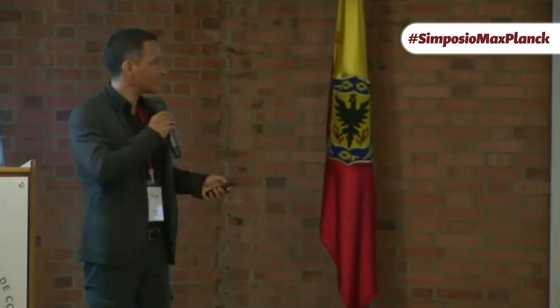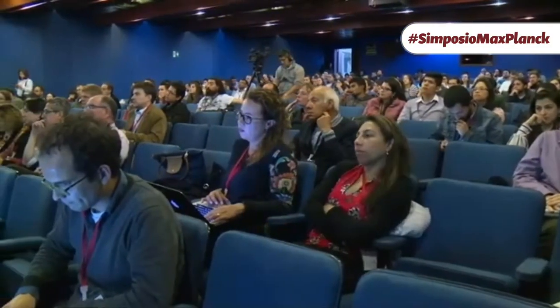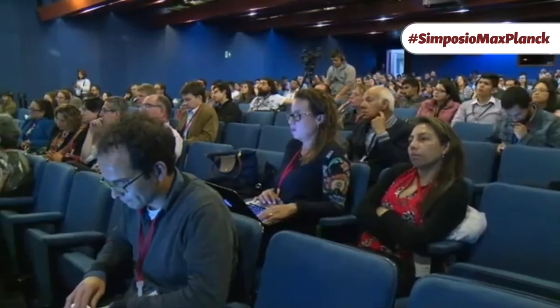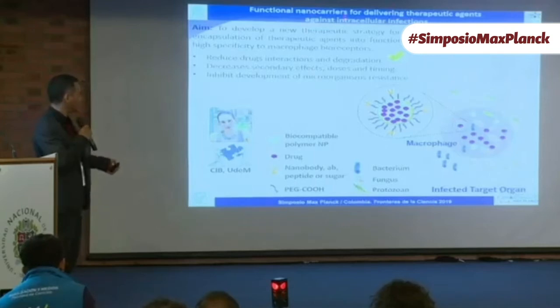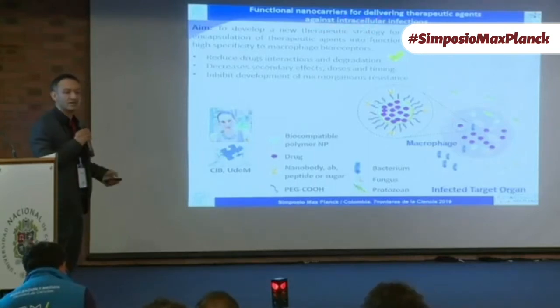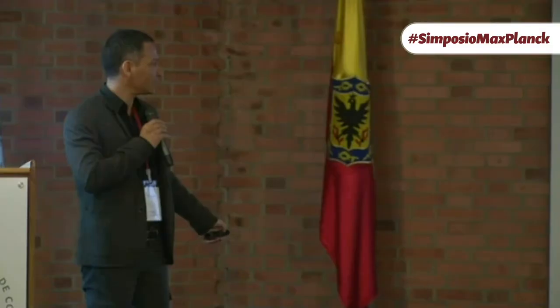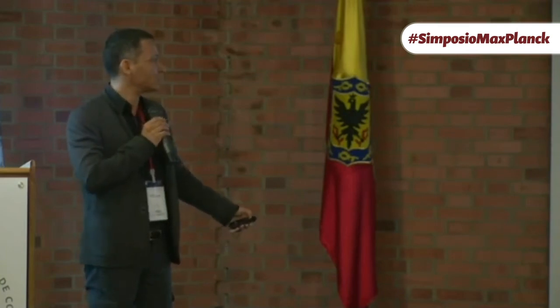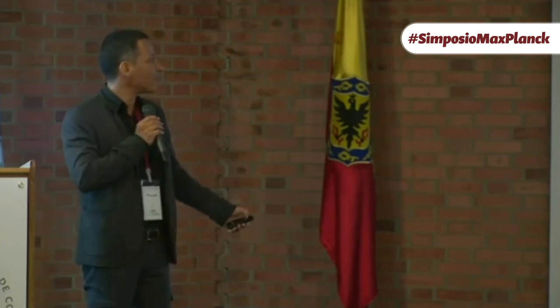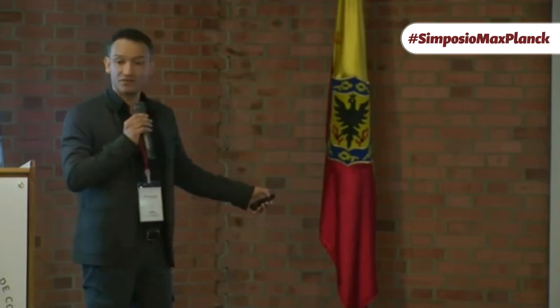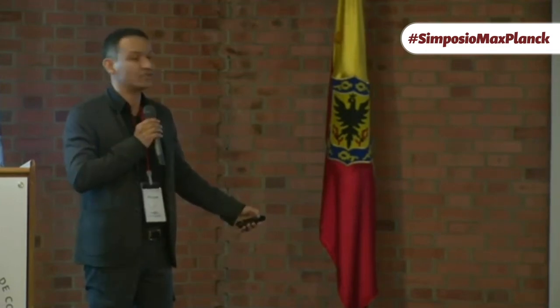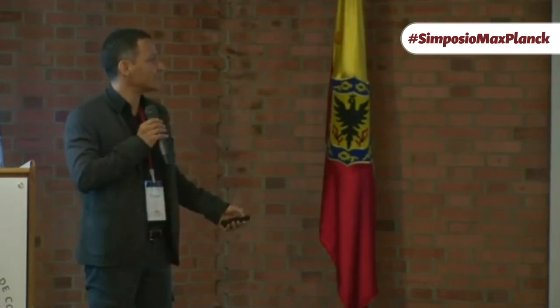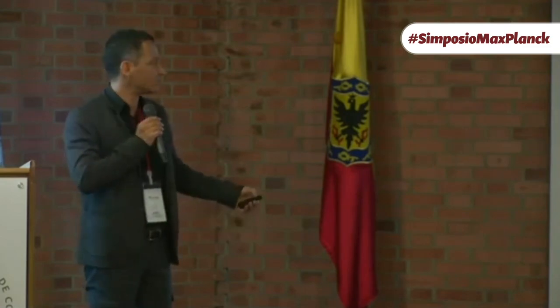So to finish quickly, this is the last example. We're using polymeric biocompatible nanoparticles from PLGA and PLA to encapsulate drugs to fight intracellular infections. For this purpose, we are using Histoplasma capsulatum as a model of the infection. We're using itraconazole as a drug model. And at this point, we optimize the formulation. We estimate the drug loading capacity and the encapsulation efficiency. And we expect to functionalize with nanobodies as a part of the project.